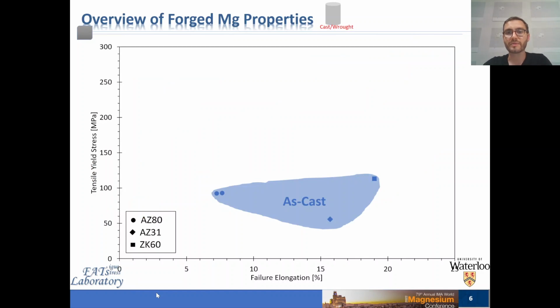Firstly, I'd like to describe the evolution of the properties from the as-received material to the forged material. It is impossible to have one parameter which captures all of the effects that go into this process, but in general, the microstructural modification due to the processing treatments generally has a mutually exclusive relationship between strength and ductility. In a very general sense, if the strength increases as a result of some processing technique for magnesium, generally it is at the compromise of ductility, as many of you may know.